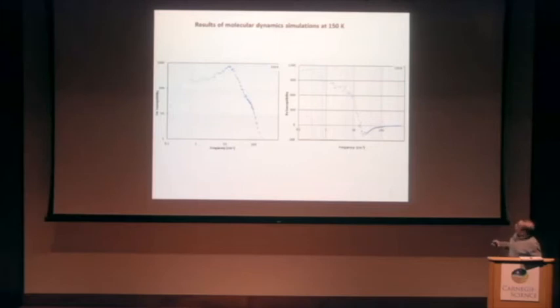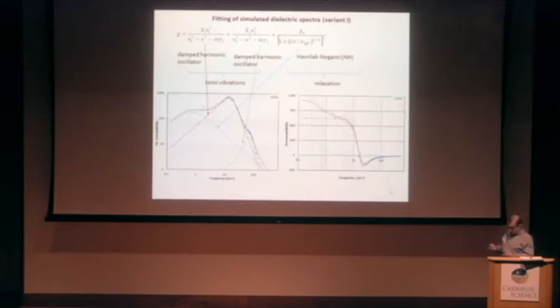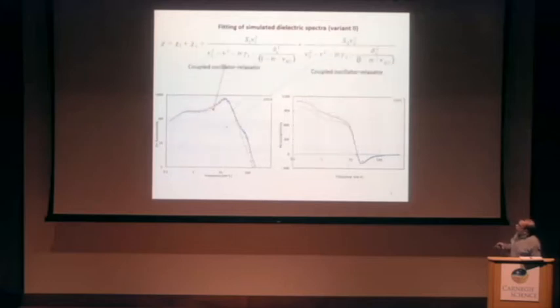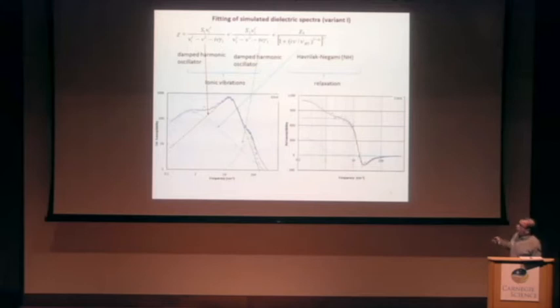You can see clearly two lattice modes. They are here at 1 and 2 with negative real susceptibility and 1 relaxation at lower frequencies. And this figure looks like experimental data, and we treated the results as experimental results. Thus, we use simple models. In this particular case, this is the model of damped harmonic oscillator, and each mode was described by one oscillator, and the relaxation is described by the Havriliak-Negami equation, which is the most general relaxation equation.